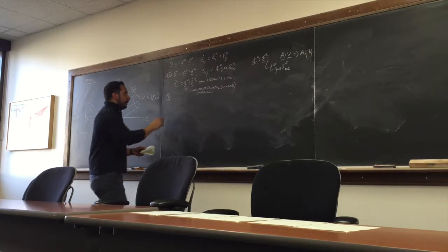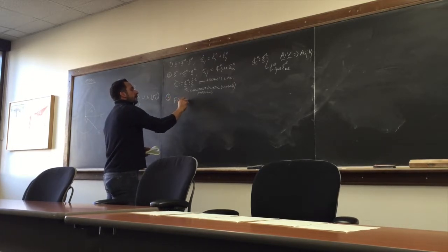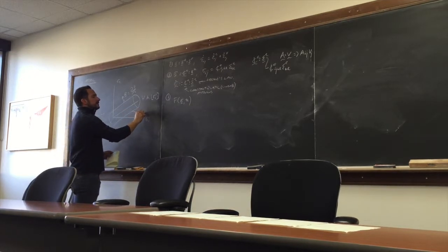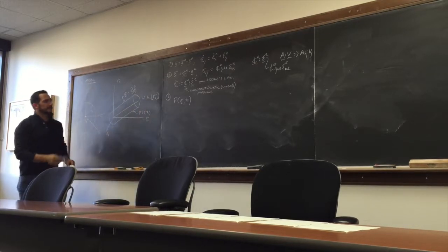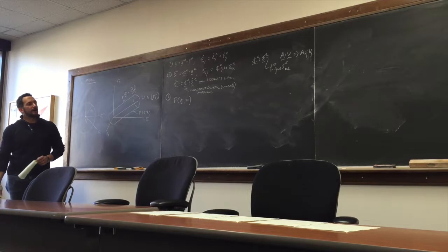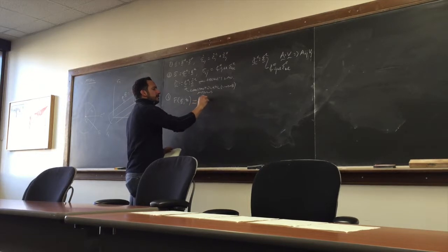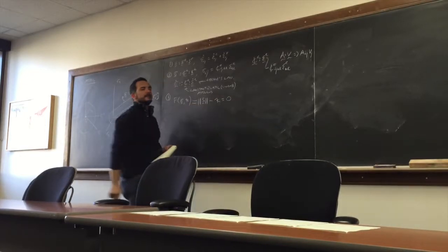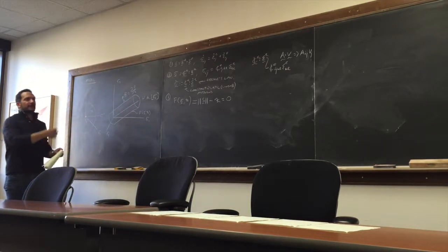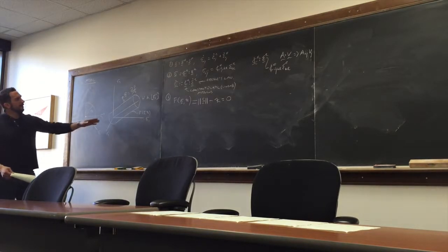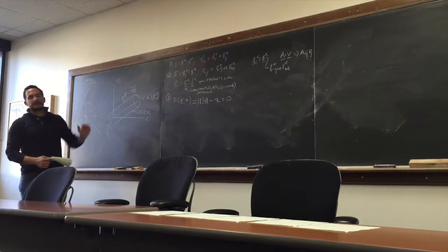Third ingredient, flow, right? You need to say what defines flow. So you have your elastic, your yield surface, F of sigma and kappa, that you know it's a cylinder now in three-dimensional principal stress space. And this is defined as the L2 norm of S minus kappa has to be equal to 0, right? That defines a surface in 3D principal stress space, and that's your cylinder of radius kappa. And it's an infinite cylinder along the hydrostatic axis. We saw that it doesn't matter how much pressure we put on this thing, it's always the same, okay?